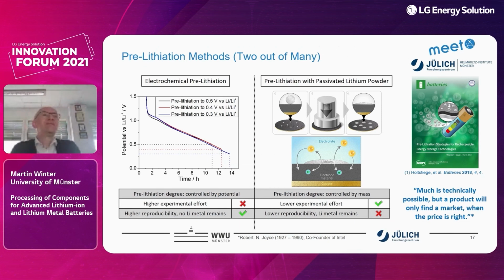The pre-lithiation by electrochemistry needs a higher experimental effort, but higher reproducibility is also given because basically, if you are accurate, no lithium metal remains. The pre-lithiation with passivated lithium powder depends on how precisely you can dose the powder. It has a lower reproducibility and also some lithium metal remains, depending on how much lithium metal you are using. Still, I want to mention that this paper actually has been awarded as a paper in Batteries. That's a journal. But I want to mention that much is technically possible, but at the end you have to think about a pre-lithiation method which is somehow incorporated in the process that you have in your cell manufacturing, because only then can you find a market where the price is right.